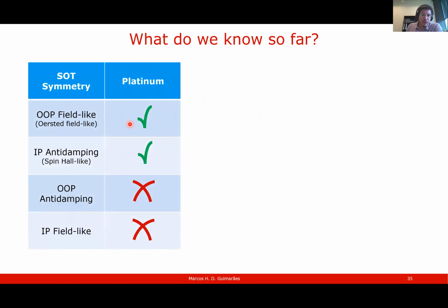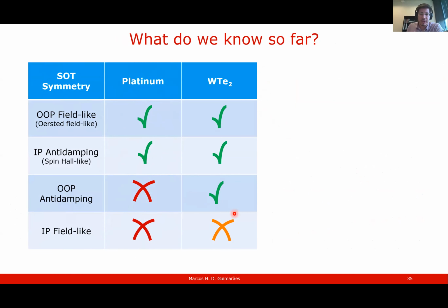So what we know so far, the spin orbit torque symmetries, all the symmetries there. For platinum, we just have the standard out-of-plane field-like and the in-plane anti-damping-like torque. The others are not allowed by symmetry. For the tungsten ditelluride, we observe the out-of-plane anti-damping, but not the in-plane field-like torque, even though symmetry allows.